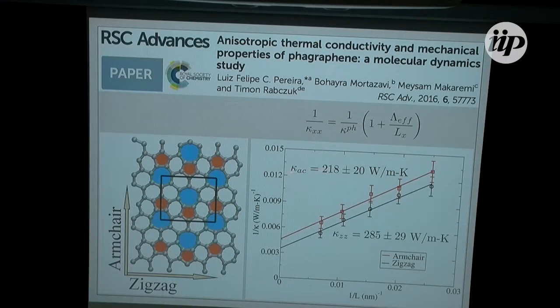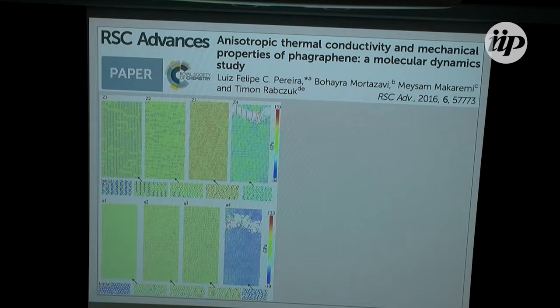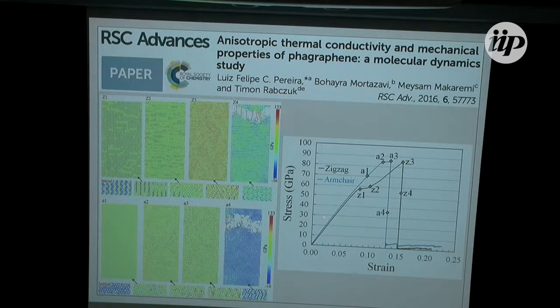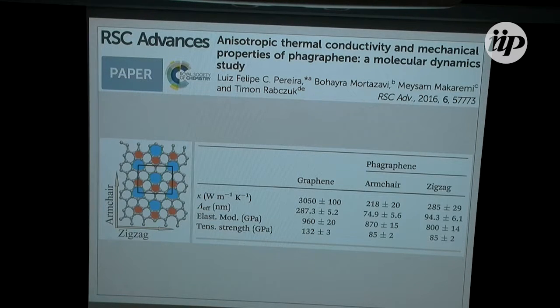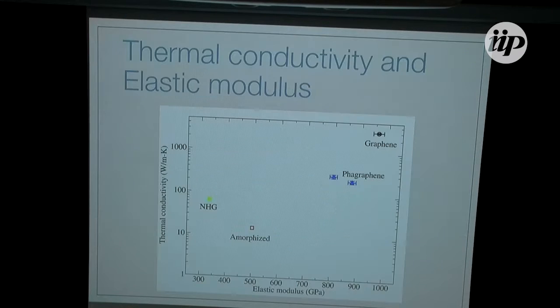In a given direction that we call the armchair, in analogy with graphene, you have a thermal conductivity of about 220 watts per meter Kelvin, and in the other direction about 290 watts per meter Kelvin. We also expect the material to have an anisotropic elastic strength, and this is indeed the case. It breaks differently if you strain it along the armchair direction or along the zigzag direction. Then we summarize all of this and I put it in my graph. It has two different values for the thermal conductivity, but also two different values for the elastic modulus.